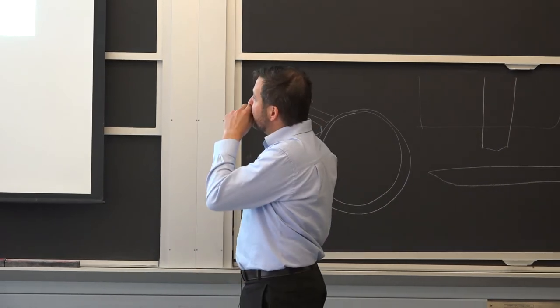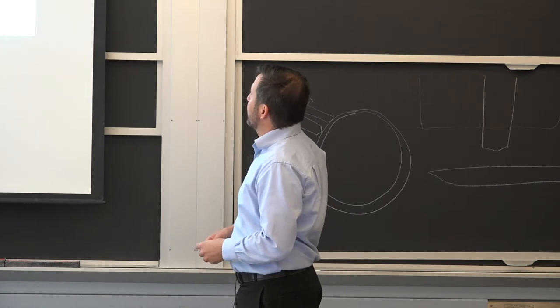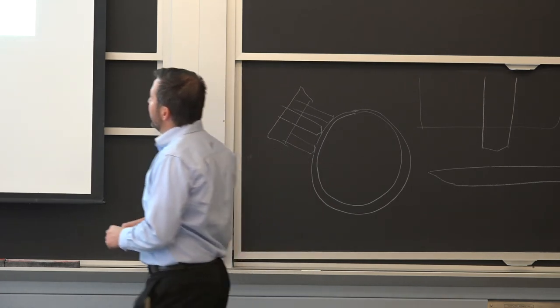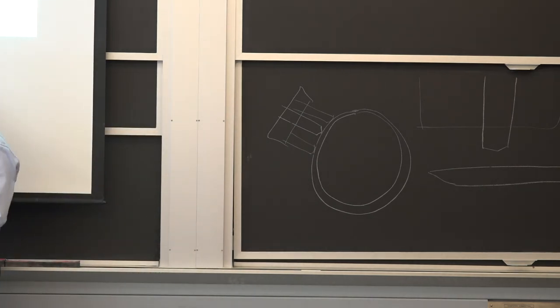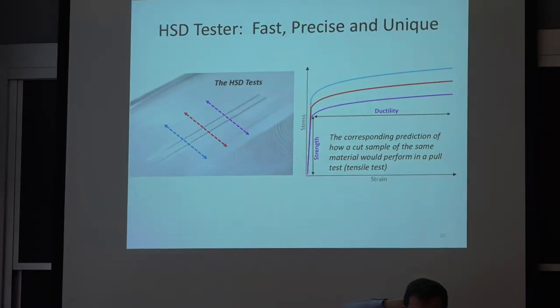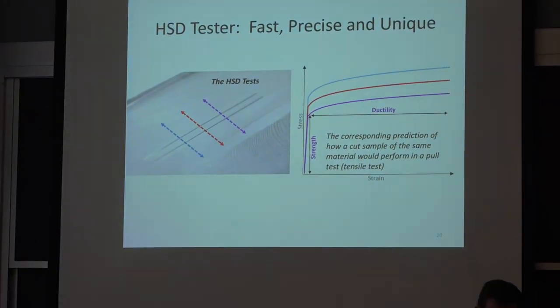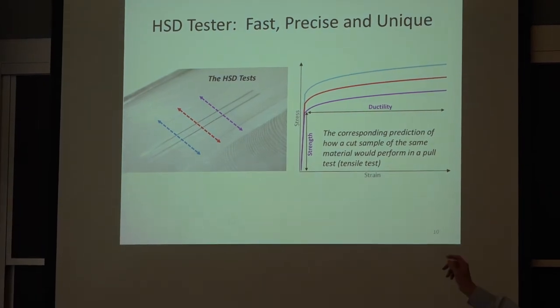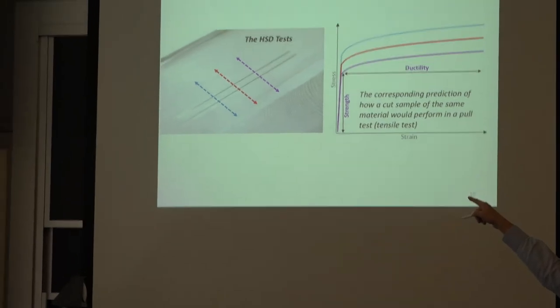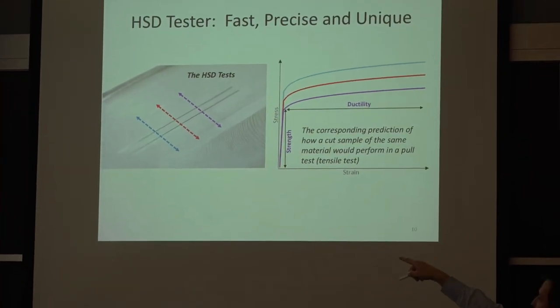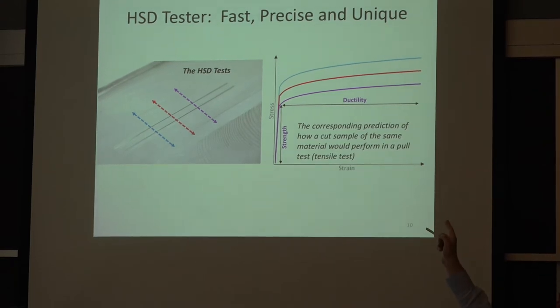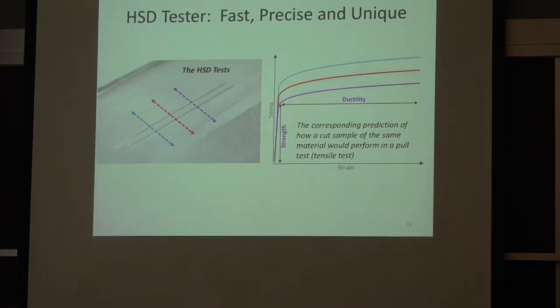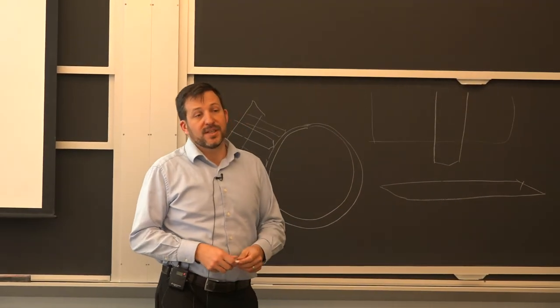Now, what gets very complicated here to some extent, and again, this is just a copy. So we're saying from this test, you get a pull test curve. So you get what you would obtain normally in the lab. And that's not very well explained here. This is just the way it is. But for you guys, essentially, each time that we profile those two grooves, in this case that I made, we're able from just those two grooves, where the blue line is, to make a stress strain curve. And what that means is we're able to see the evolution of yield strength during the test, which is very, very unique. Essentially, you just plot an evolution. So when you go over that weld here, you're able to pick up the signature of the weld.